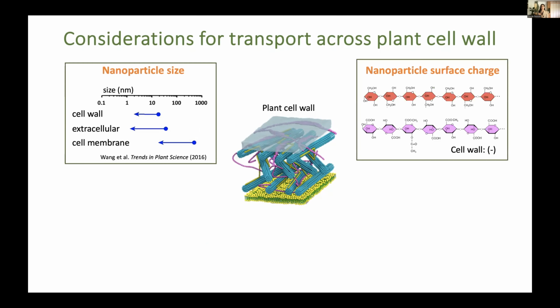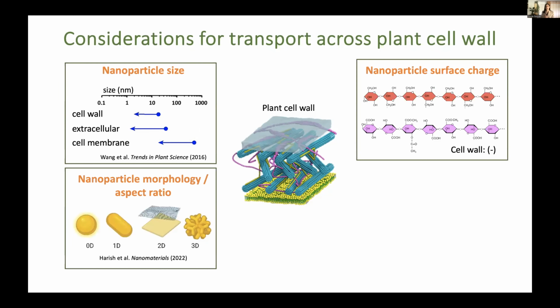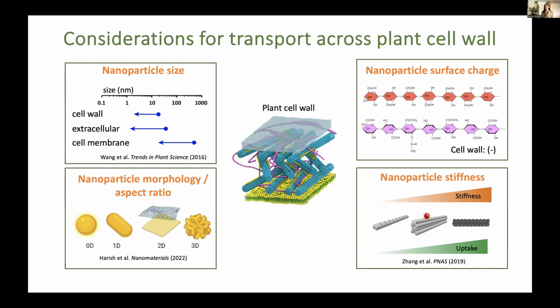Another parameter that's important is the nanoparticle surface charge. We know that plant cell walls are highly negatively charged, so it's been hypothesized that positively charged nanoparticles can more readily associate with plant cell walls and then internalize into cells more efficiently. In addition to size and surface charge, nanoparticle morphology and aspect ratio are important to consider as well. While there are some studies claiming that one-dimensional high aspect ratio nanomaterials may be more efficient in entering plant cells, there are also studies showing spherical or three-dimensional mesoporous structures being able to enter plant cells as well. And lastly, nanoparticle stiffness is an important property that has been receiving less attention so far, mostly because it's hard to measure, but it's also important, and it's been shown that stiffer nanoparticles have an easier approach in being able to penetrate the cell wall.